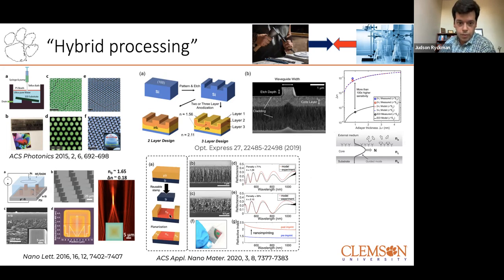But when we compress the film mechanically, we reduce the fraction of air, and therefore the porosity goes down. The refractive index has to go up. So we now have a mechanical means of tuning refractive index on the surface of a chip. You see here this example, the relatively large area uniformity, several millimeters squared, kind of handheld chip type of measurement here. And this is a pretty broad effect. Oh, my lights came back on. So I'm going to revisit this one in just a second.